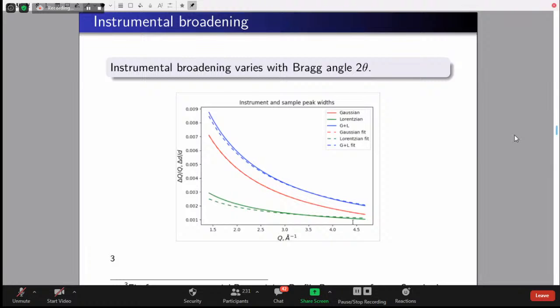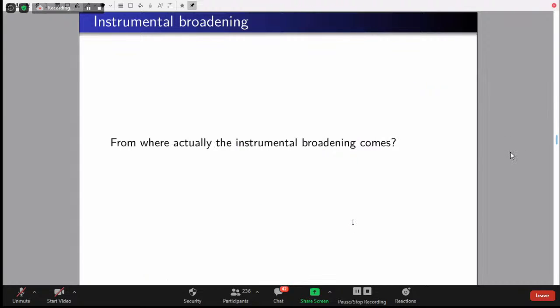If you are using a peak at higher 2 theta, then we are introducing broadening which is coming from the instrument, not from the sample itself. So the instrumental broadening will be small at a lower 2 theta. Only those peaks can you consider for analysis when you are calculating the size or strain. All right. So what are the other things which are going to contribute more to our instrumental broadening?